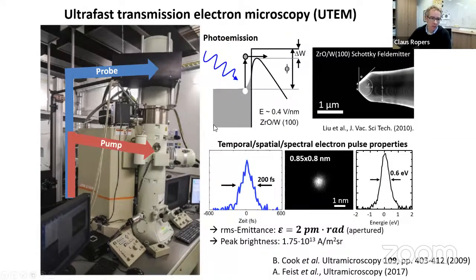Yes, the microscopic emission mechanism, I should just mention quickly, is linear photoemission over the barrier of this Schottky field emitter. So you heat this tip to moderate temperature above 1000 Kelvin. So you have a slight Fermi tail in the electron distribution here, and you use a photon energy such that electrons are emitted slightly over this Schottky barrier produced by applying a strong static field to this tip. It's important to note that this is a linear photoemission process because in this way you can use an arbitrary structuring of the electron pulses. So you can use femtosecond pulses, picosecond or nanosecond pulses, depending on the desired temporal resolution for the particular experiment, or even continuous wave excitation of the source.